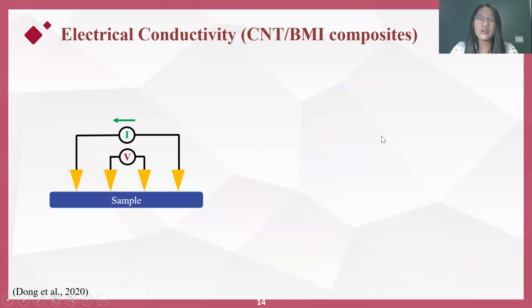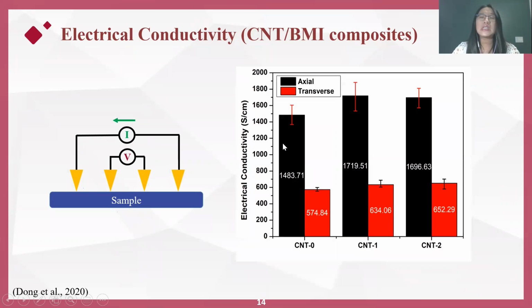To characterize the electrical conductivity, a 4-probe configuration was set as shown here. Similarly, we have seen substantial differences in the electrical conductivity when measured in the axial and the transverse direction. Once again, this indicates partial CNT alignment. We see that both the water-assisted groups, the CNT1 and CNT2 BMI composites, showing higher conductivity at around 1700 Siemens per centimeter. And this is about 16% increase when referenced to the control group.